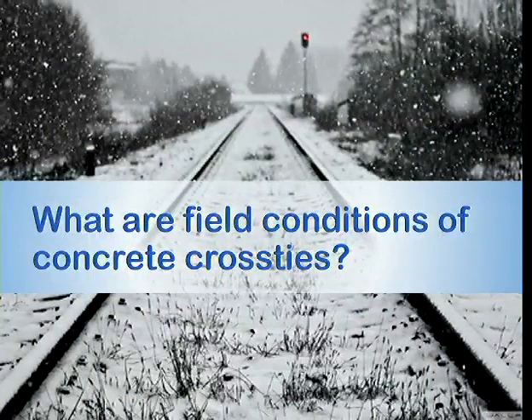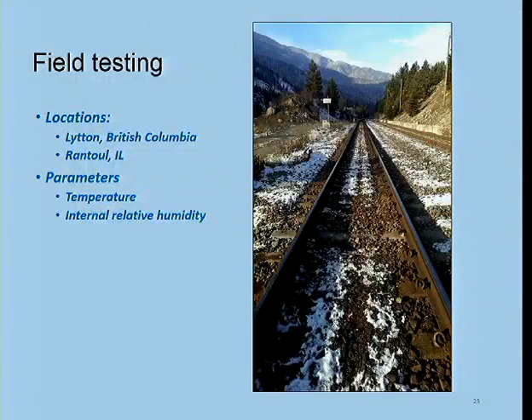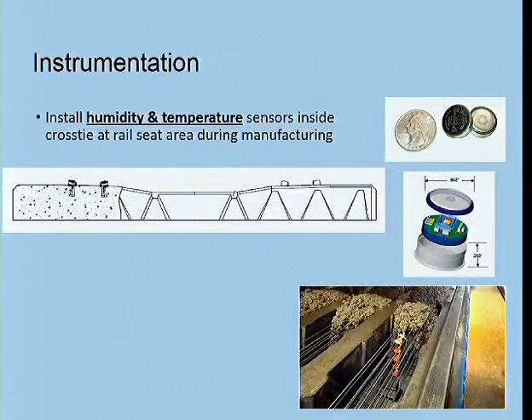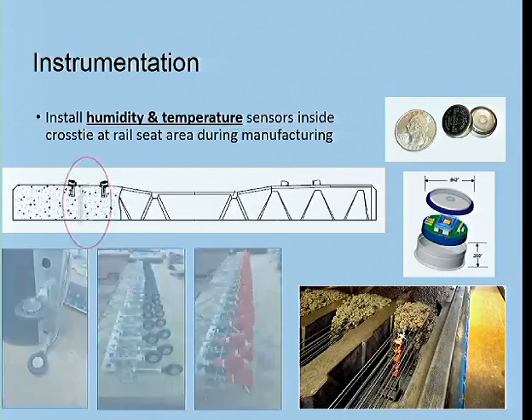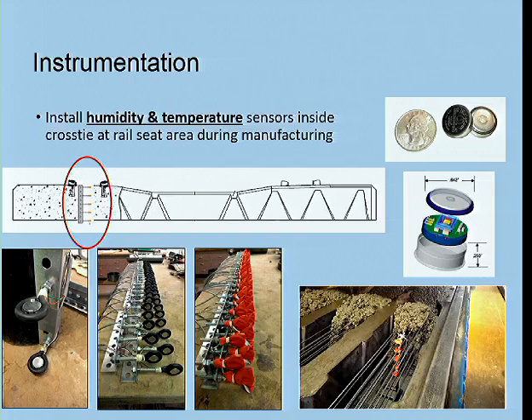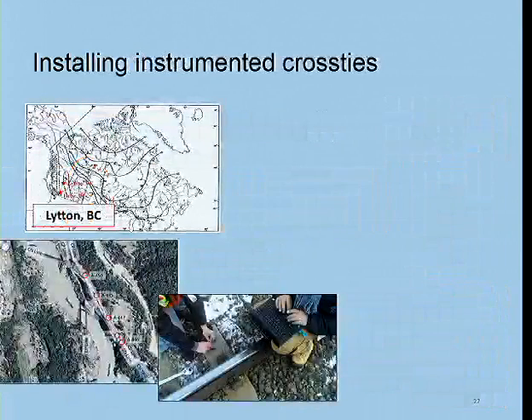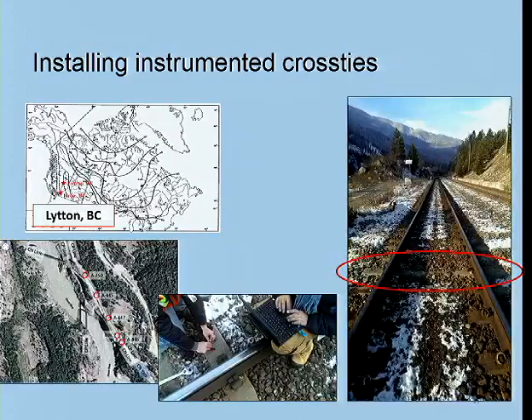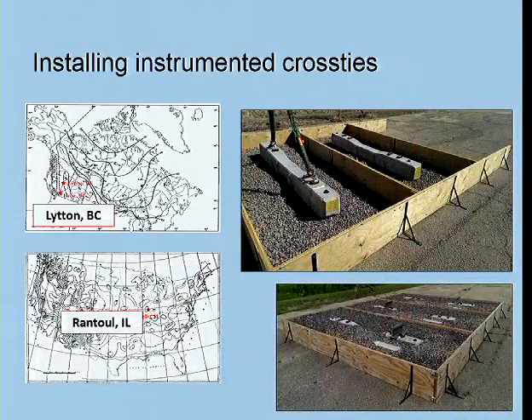The next idea that we want to think about is the field conditions of concrete. We had a chance to have a field testing program at Lytton, British Columbia, as well as here in Rantoul, measuring the temperature and internal relative humidity inside the concrete ties. We used little teeny sensors that measure temperature and relative humidity. We cast these inside concrete ties and shipped them out to the field. You can see here the kind of trees that were established so we could get depth-wise sensitivity to the change of properties. And we installed these in track, and then at Rantoul in ballast that was in boxes, as much of a replication as possible of the kind of conditions that we get in the field.